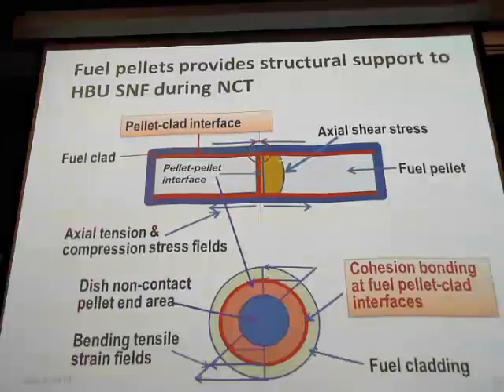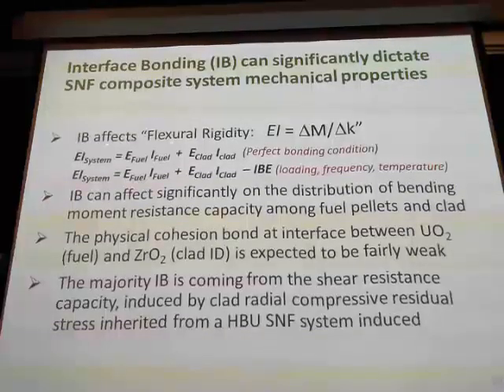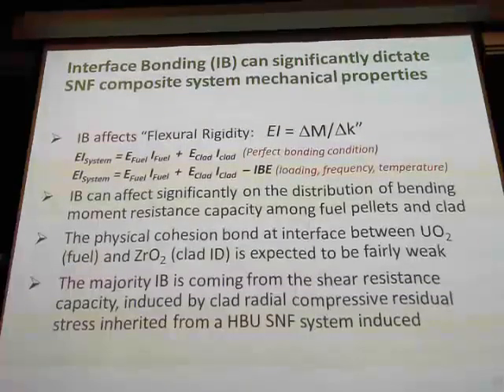This is a schematic diagram showing there's a pellet, there's the interface, and under bending you have the normal stress, tension and compression. One side is compression, one side is tension. And the shear stress is normally one order of magnitude less than the tension. Most of you right now have an end dishing to avoid the bamboo effect. So really you can see the pellet contact surface is very limited, so the bonding between pellets is very, very small. The bonding efficiency we talk about, the interface bonding: if they are perfectly bonded, you can do a summation of the two systems, fuel and clad. But if it's not a perfect bonding, you need to have a penalty. This is why we use experiments to define it.